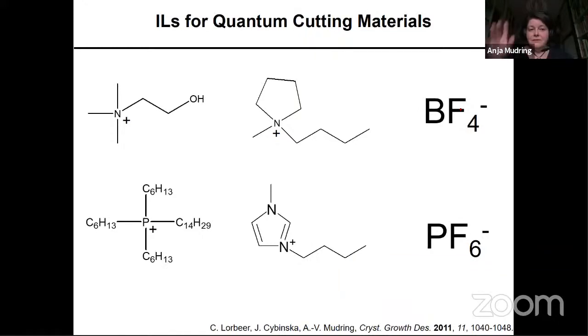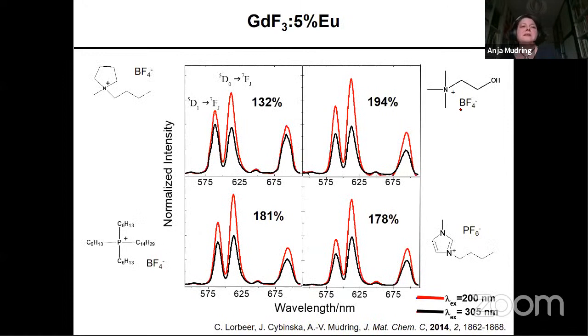And we studied all the different combinations in this microwave reaction to make the gadolinium fluoride, and then measured the quantum yields. And we were really happy that one of the experiments gave us a quantum yield close to 200%. So that is really close to the theoretical limit. We were totally excited. There were others where the quantum yields weren't that great.